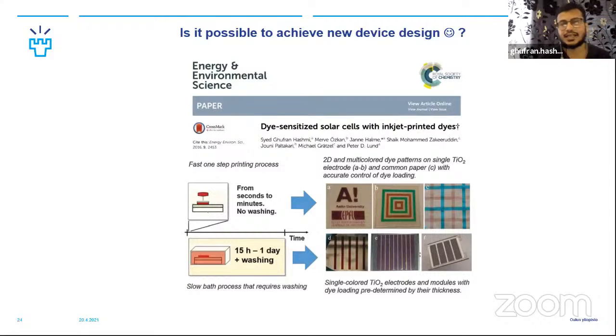And even in this kind of co-sensitization method which is currently implemented, to the best of my knowledge, you make two different solutions of concentration and then you mix them in a proportion by volume. But when you sensitize, the dye loading volume of both dyes is still unknown. But inkjet printing allows you to systematically make a loading with a controlled volume. So that could also affect the overall process.